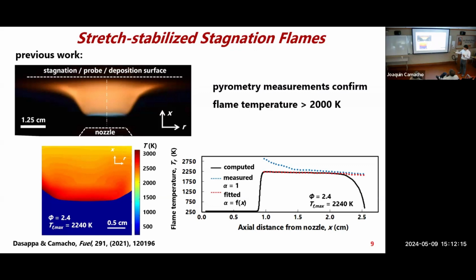If we apply this computational model, it would predict that you're burning at about 2,200 Kelvin or so. And we're able to take measurements based on the black body radiation that indeed we are much hotter than typical flame temperatures. So this flame is very nice to give us a relatively simple flow field with flame temperatures much hotter than typical flames. That's what I've been using to look at the particles forming. There are particles here, and this is black body radiation of solid aerosol. We're going to look at the differences between soot formed in this regime, high temperatures, versus typical flame conditions.